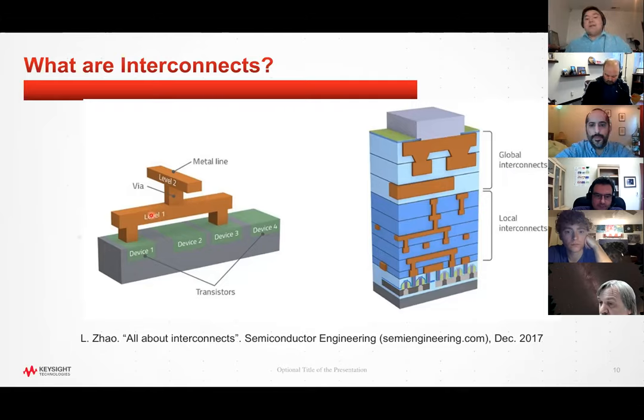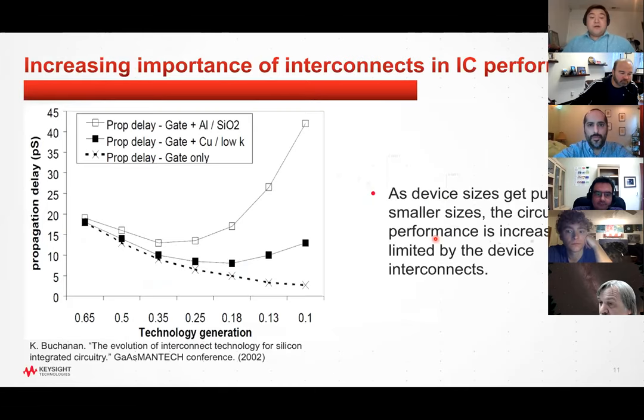And it's very common now to make these 3D layered structures where you have transmission metal lines that run horizontally, and then what are called vias that connect the layers together. And you can build up these structures. The reason that you do these stacked layers is basically so you can fit more into a smaller space. And the common material being used for these interconnects now is copper. And basically, as our technology advances and we can make smaller devices, the performance of these circuits is increasingly limited actually by the interconnects rather than the devices themselves.